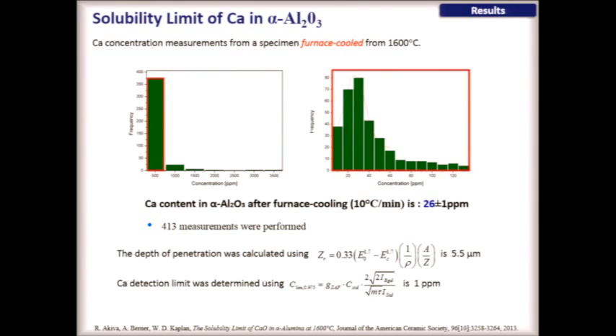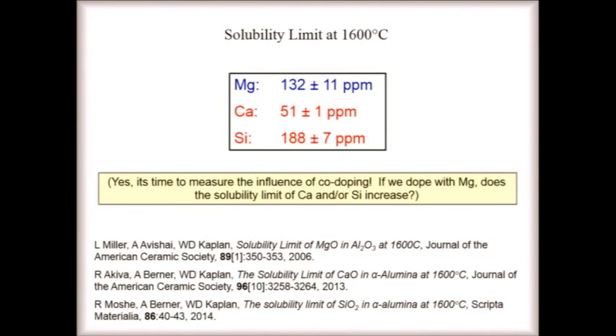So that's not the solubility limit at room temperature, it's a solubility limit at some temperature when diffusion becomes no longer important. And we don't know what that is, but that's the problem of trying to do this after cooling at the rate of the furnace. I just comment that so few proper experiments have been done on quench samples. I've been complaining about this for decades.